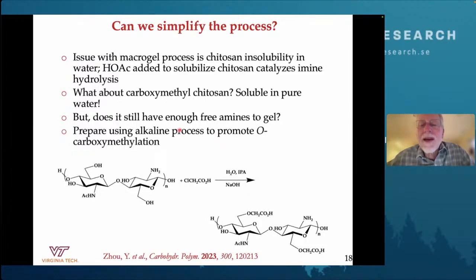The hypothesis we had was the acetic acid we needed to solubilize the chitosan was catalyzing the hydrolysis of the imine crosslinks. So we had to get rid of the acetic acid.